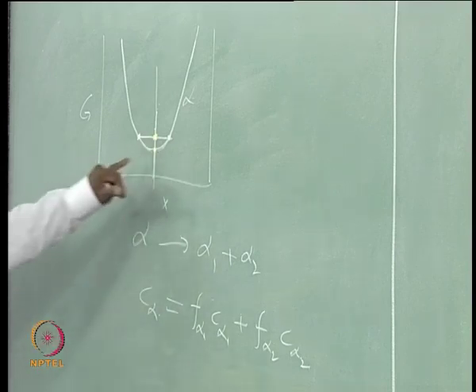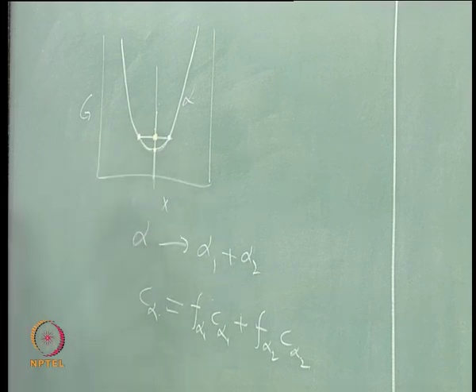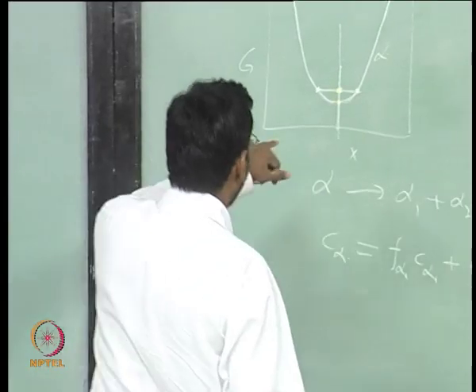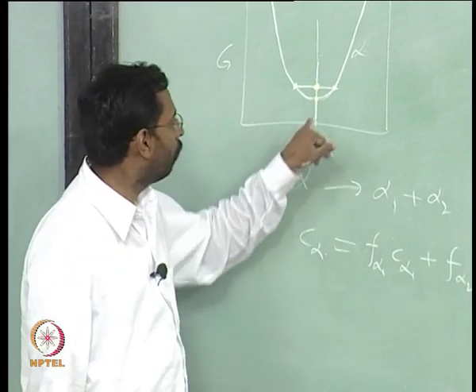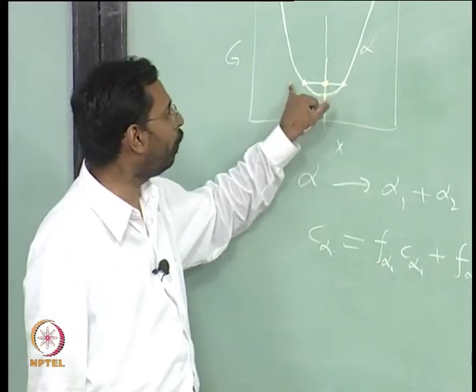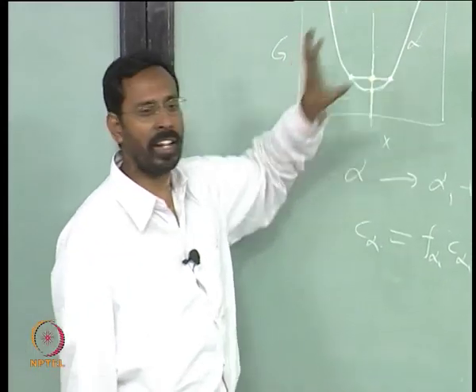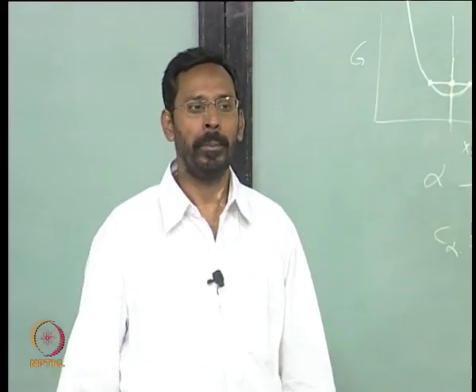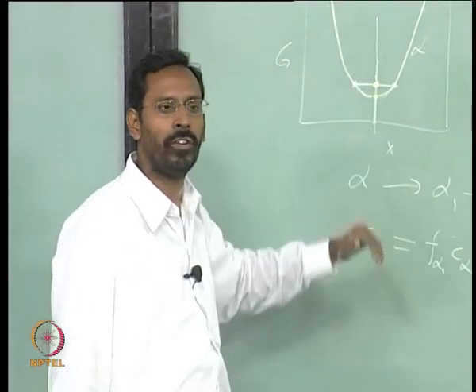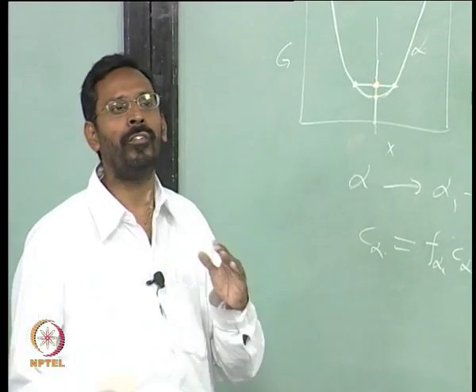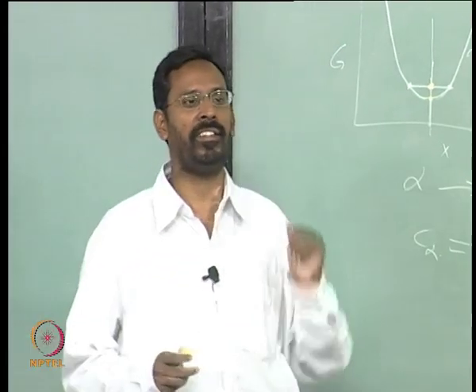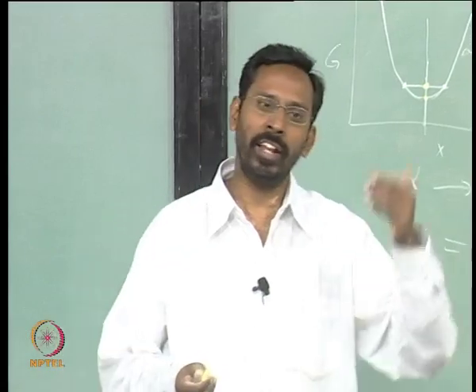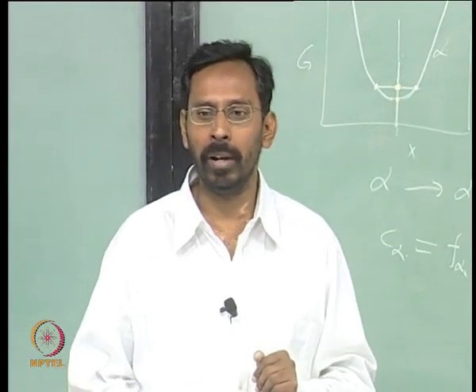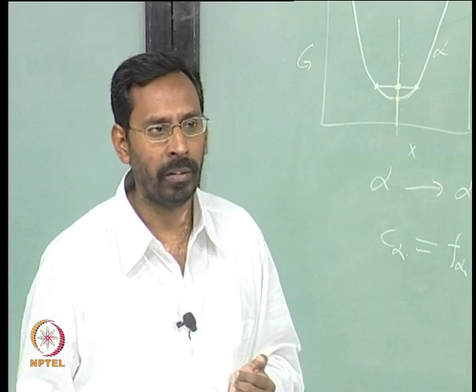As a result, such a decomposition into two is not usually observed, because there is no driving force for such a thing to happen. So, for a single phase alpha to split into two phases in this kind of situation does not happen, because there is no driving force. Because of such a decomposition, the free energy is actually increasing rather than decreasing. We know that every process where there is a decrease in free energy is favorable, and an increase in free energy is not favorable, is it not?